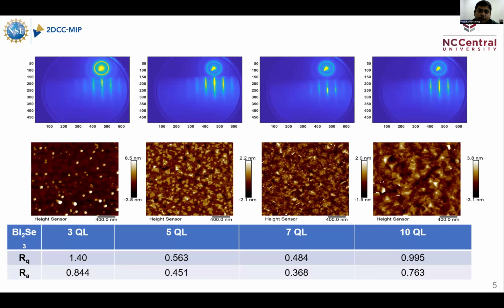This 5 quintuple layer sample was behaving abruptly. I didn't change it because I didn't get a chance to repeat the AFM before coming back here. I'm still trying to get the AFM done, but this is the data with the old sample. We found that with increased thickness, surface roughness was reduced. But for the 5 nanometer sample, the RHEED pattern shows the brightest streak. We confirmed the same with Raman and UV, but we repeated this experiment and got the exact thickness, and the rest of the data was in a trend.